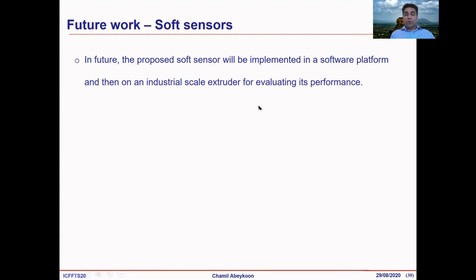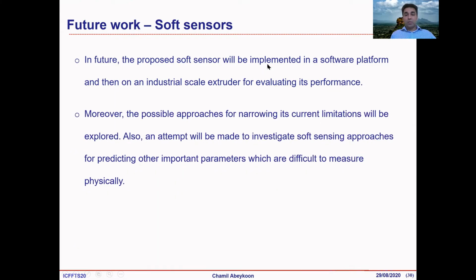We're going to implement this soft sensor as a plug and play device. Once we have the inputs measured, and more importantly, these inputs are really readily measurable parameters, screw speed and set temperatures are the key parameters that you can measure without any problem, without disturbing the process in industry. So we can use those parameters and input them into our model. Then it can automatically or easily predict the melt temperature profile across the melt flow, although we cannot measure it using a physical sensor. So our next target is to implement this soft sensor as a plug and play device.